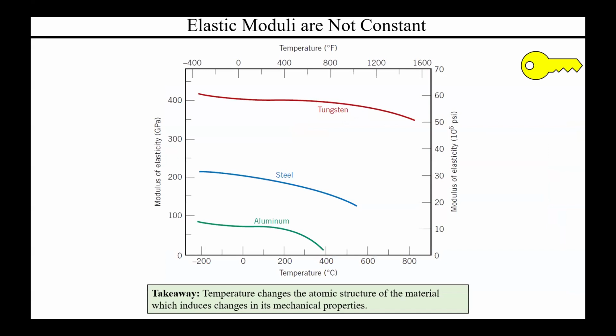Another important aspect is that elastic properties, and mechanical properties in general, are not constant. They depend on many things. Temperature is an easy one to visualize. You heat it up and obviously it's changing its structure. In this case, you could have tungsten, which drops a little bit from negative 200 to 800 C. Aluminum sees an even larger drop. Part of the reason for that is that 800 C is not really close to the melting temperature of tungsten, whereas with aluminum, it's beyond it.